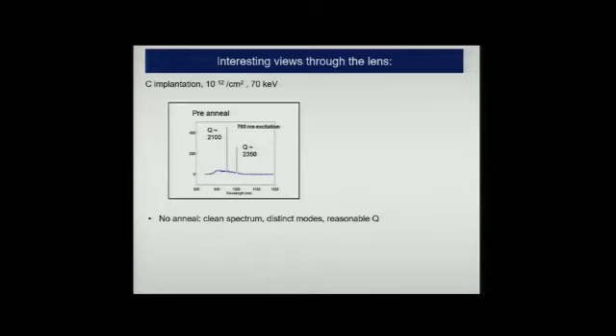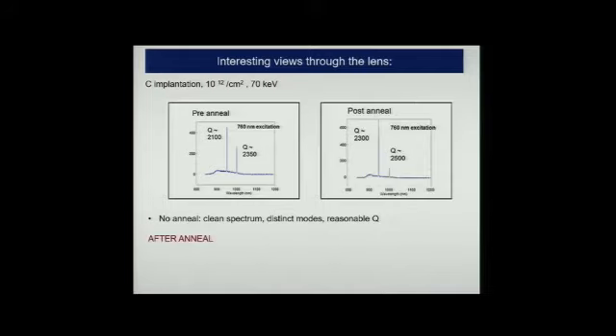But we were interested. So we take the self-same device, and we anneal the self-same device at 750 degrees for half an hour. And we see a variety of different results. But for this device, this particular device, we see this. Tell me what you see that's interesting. What's different and what's interesting? And what's the most interesting, do you think?